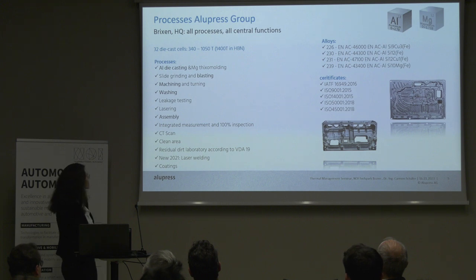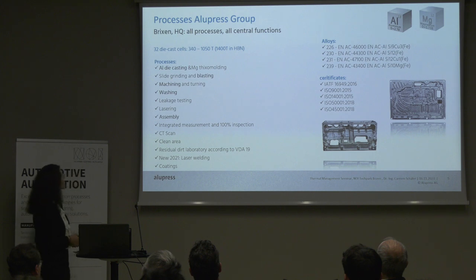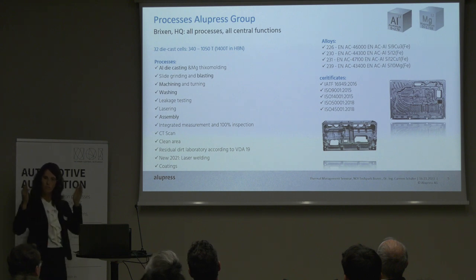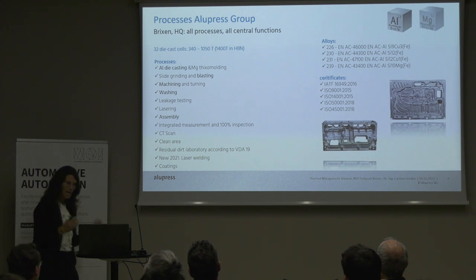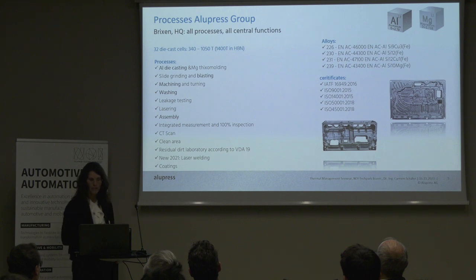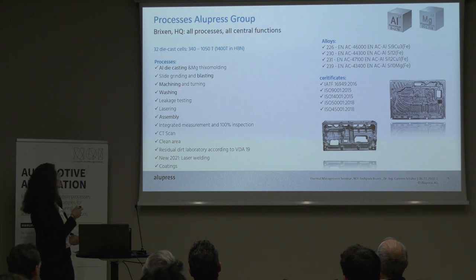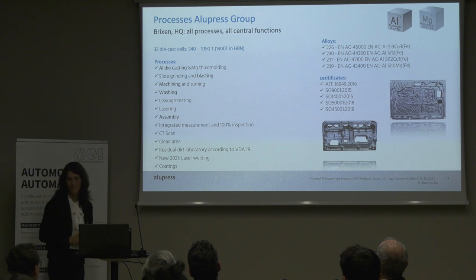The process itself, you see here: we are automotive, IATF 16949, starting from the melt, going into the first cast part, punching, then blasting. We need to modify the surface because particles are a big issue since it's electronics. We need to remove them. That means everywhere you will find washing steps, machining and assembly, of course, and a huge part here is all this issue about technical cleanliness.